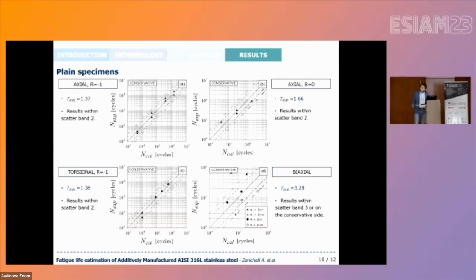With the only exception of this value, which is related to loading ratio -1 and phase angle equal to 90 degrees, which is at least on the conservative side of the graph. So in order to see the accuracy of the results we obtained, we can use the root mean square error method.